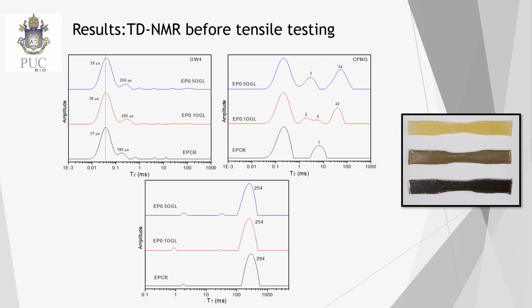From the distributions, we can see that the mobile region of the resin, the chain segments with T2 of 7 milliseconds, are greatly influenced by the presence and the concentration of the graphene, dividing into new relaxation domains with higher T2 values in increased width, especially for the sample which has 0.5 of graphene. This indicates that in addition to the mobility gain, the graphene filler also increased the number of different conformations of chain segments in the polymeric matrix where the density of the cross-links is smaller or where chain ends are